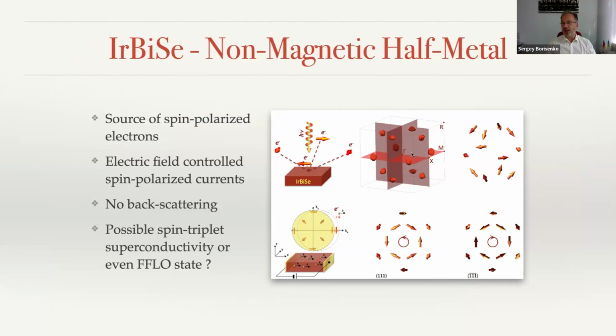So these are these point-like remnant Fermi surfaces at a very tiny doping level. So one would have 12 of those. And as I said, with a very well-defined spin character. So here I try to show that the spin is always perpendicular to the momentum. So we have in reciprocal space a unique spin textured point-like set of Fermi surfaces which have a spin chirality if one looks along 111, and if one compares in the opposite direction, there is a certain spin chirality here. And the material is non-magnetic.